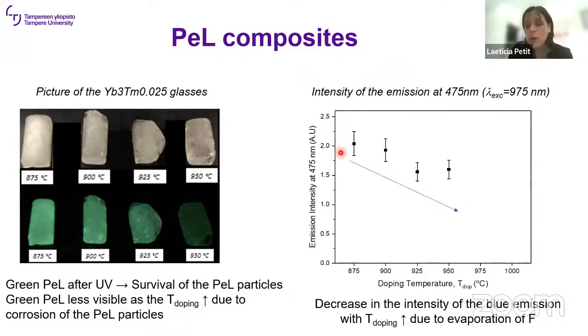At the same time, what we realized is that when you increase the doping temperature, you actually reduce the intensity of the blue upconversion. And this is due to the evaporation of fluorine. In the glass preparation, we were melting the glasses for 5 minutes, plus 3 minutes after we added the particles to get a homogeneous dispersion of the persistent luminescence. And this leads to evaporation of fluorine, and so a decrease in the blue upconversion.